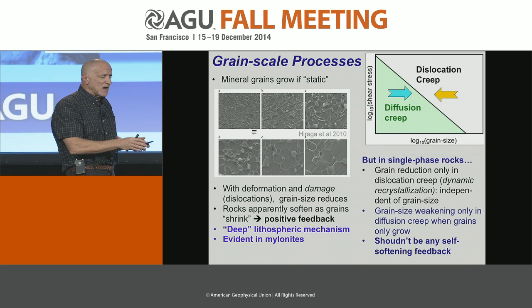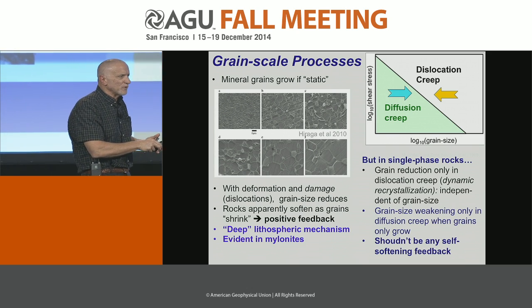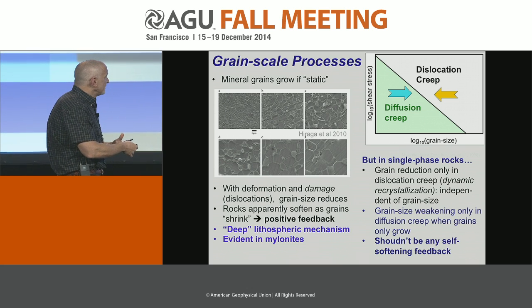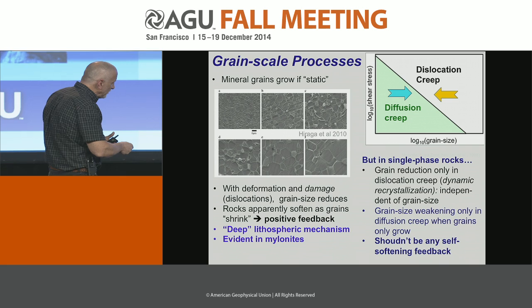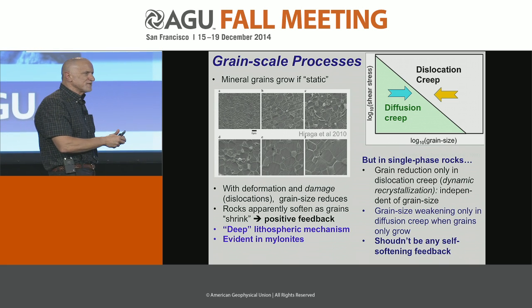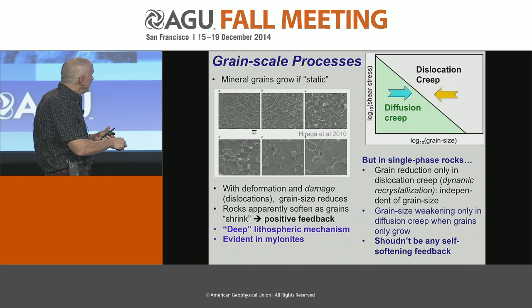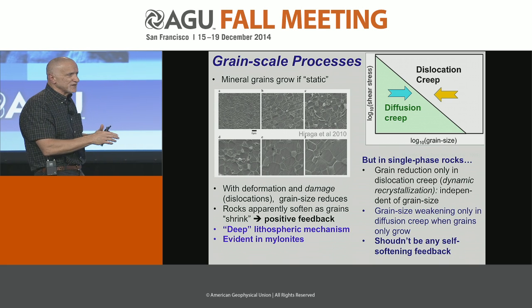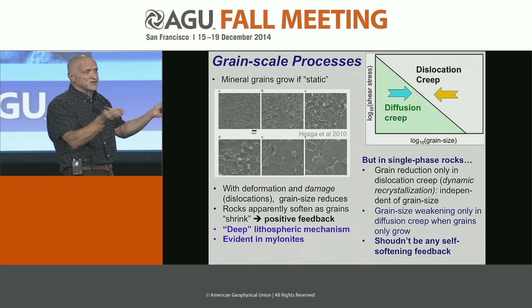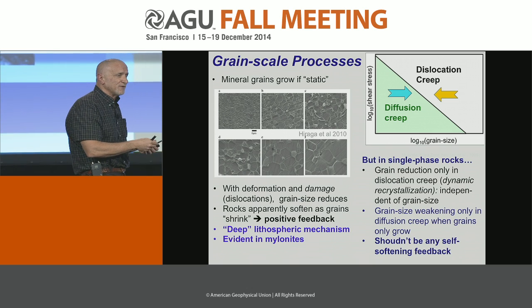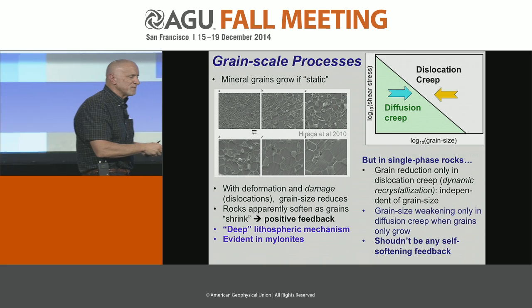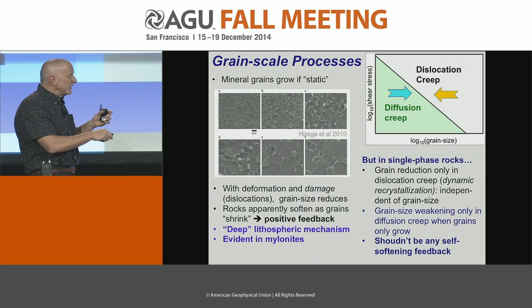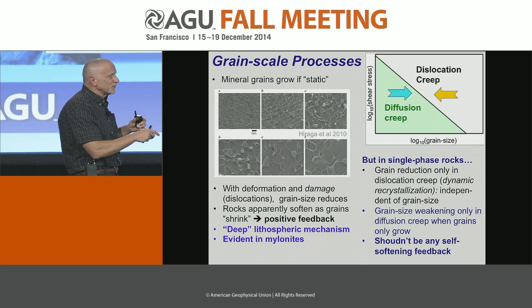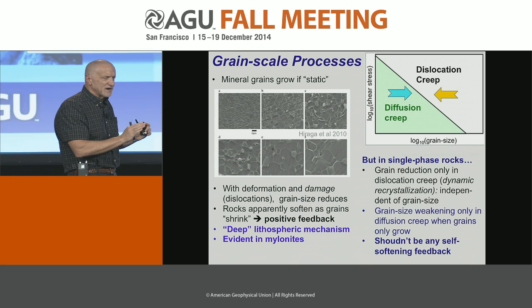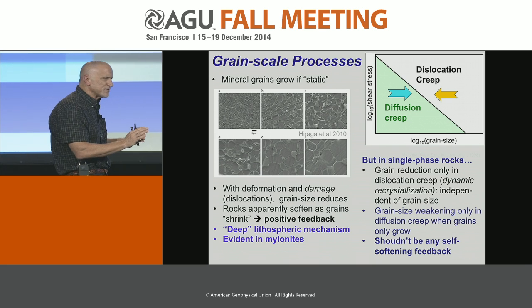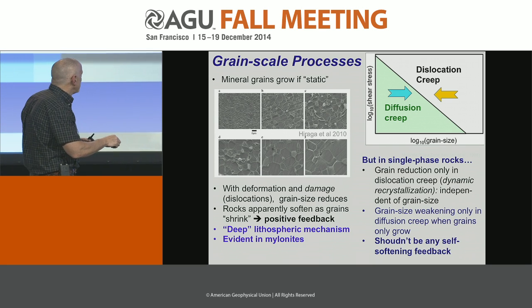But there is always this problem. It's a classic problem that people worrying about mylonites have been thinking about: in a single material like an olivine, this feedback mechanism just doesn't work. Because in a single phase, the grain reduction should only occur in dislocation creep, when dislocations are propagating around, connecting up to make new grain boundaries and make the grains smaller. But while it's in dislocation creep and the grains are reducing, the viscosity doesn't care about the grain size. So it's not softening at all as the grains get smaller.